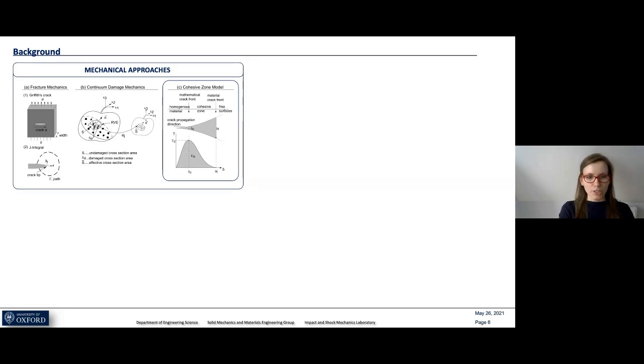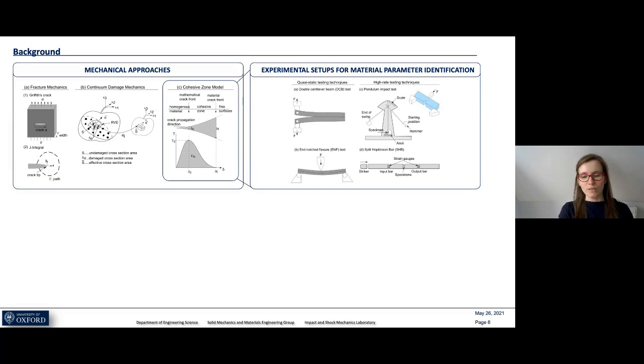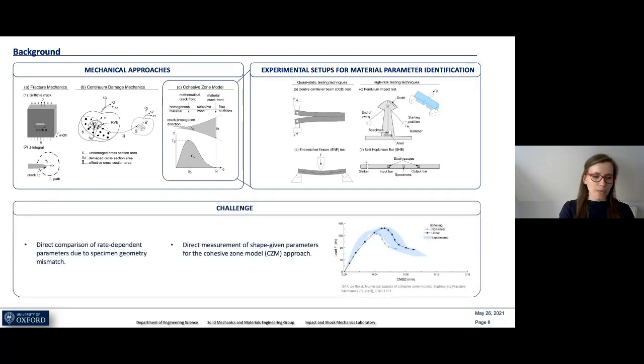For our modeling approach, we need material parameters. Experimental setups are already available for quasi-static techniques, such as traditional fracture mechanics specimens like the double cantilever beam or the end-notch fracture test, and for high-rate testing we have the pendulum impact or the split Hopkinson bar. However, to get a reliable prediction across the full rate range, we can't simply compare quasi-static DCB specimens with small compression or tensile specimens tested with a Hopkinson bar, due to specimen geometry mismatch. Additionally, researchers have found that the shape parameters of the cohesive zone model's traction-separation law also influence the accuracy of failure predictions.